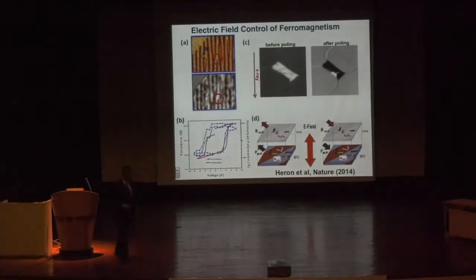This is a spin valve that we made, which is just a metal ferromagnet layer, and we put it on the bismuth iron oxide. And we switched it electrically. The red data is ferroelectric switching data, meaning I'm switching the polarization order. And the blue data is the spin valve resistance. What you take away from this is that as I'm switching the polarization order, the spin valve is also switching. I'm going to show you a little bit more of this in the next couple of slides.